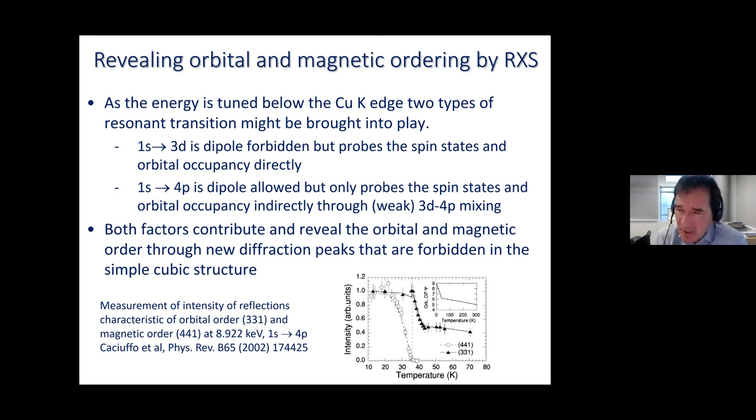And again, I should say that because these are spectroscopic transitions, the resonant process, the direct excitation into the orbital of interest, is forbidden according to spectroscopic selection rules. And because these rules are not quite perfect, you can see a small amount of additional scattering as a consequence of the resonant process from 1s to 3d.